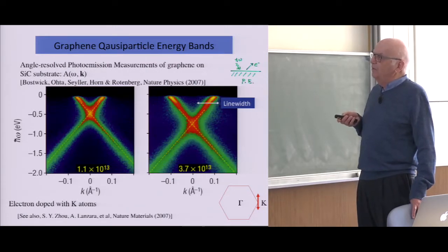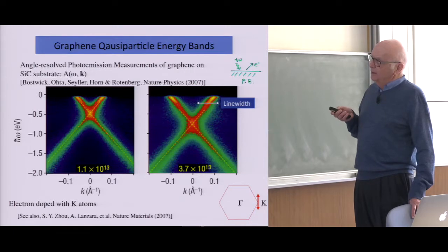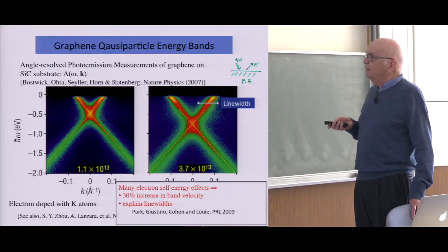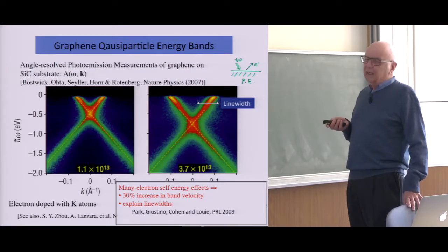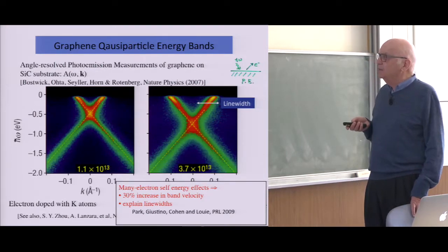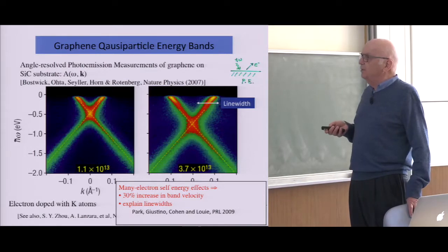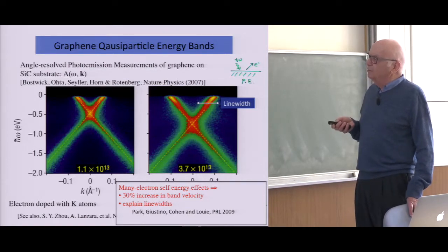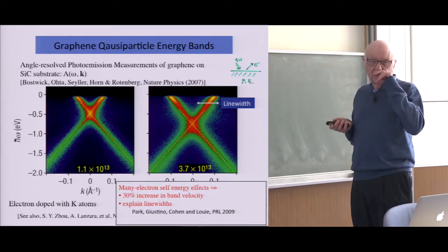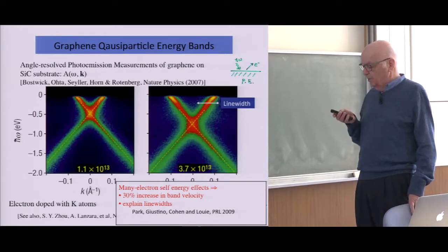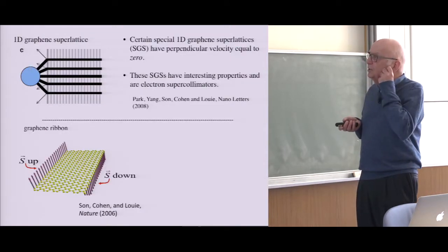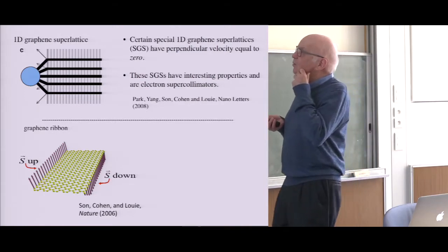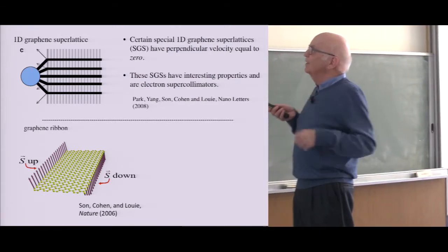So here's graphene doped with potassium, for one doping and for another doping, and you can see this linear dispersion. And in fact, if you put in the many-electron effects, the many-body effects, and the self-energy, you can see how the band velocity changes and everything. So the theory works for these materials. Let me mention just two things that we're waiting for final experimental verification.